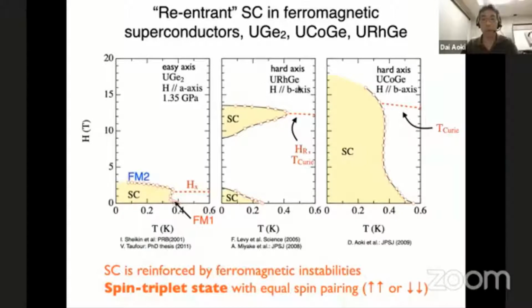In uranium rhodium germanium, it shows reentrant superconductivity here. You can see at zero field, Tc is only 0.25 Kelvin. However, if you apply a magnetic field, you can see the Tc is 0.4. So it indicates that the superconductivity is really enhanced under magnetic field. And uranium cobalt germanium. These materials were first discovered by Ann Visser's group.